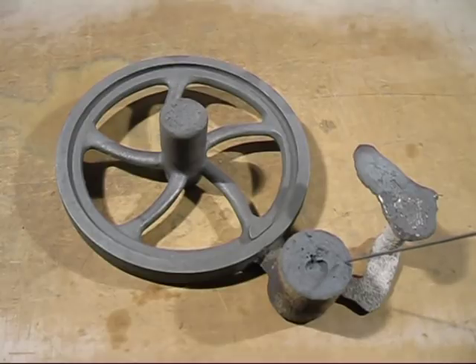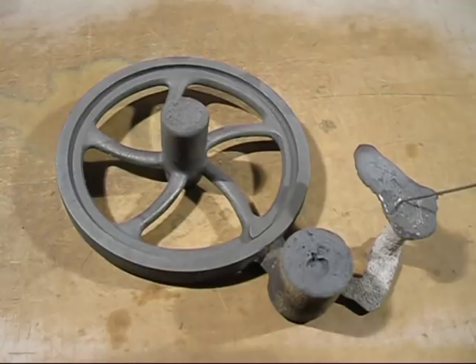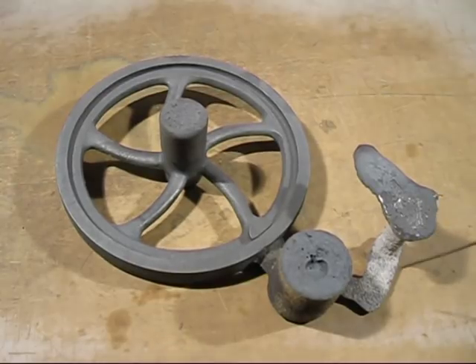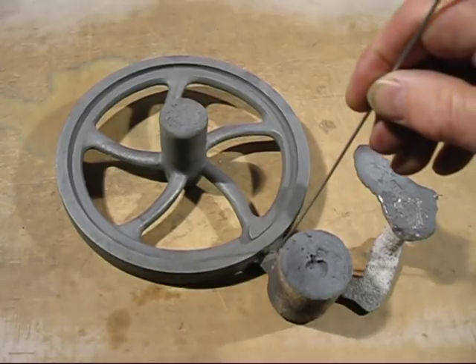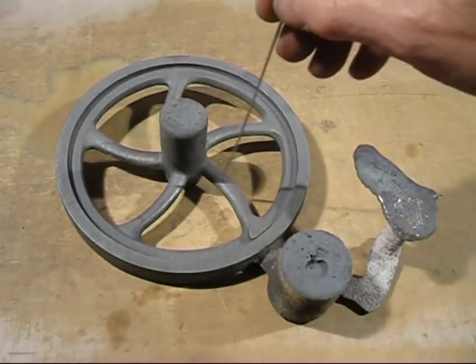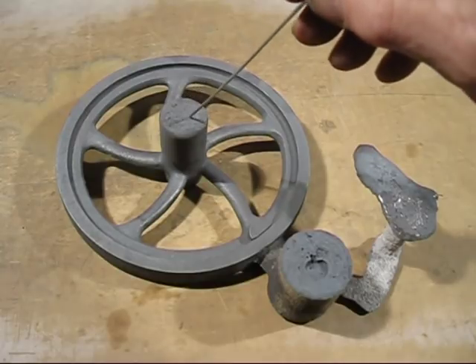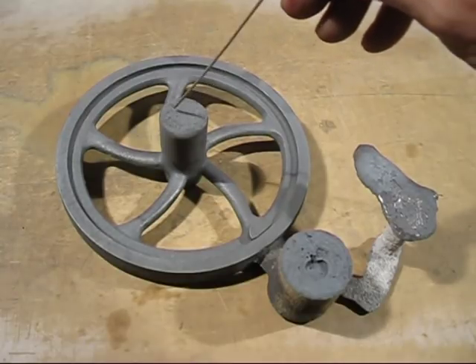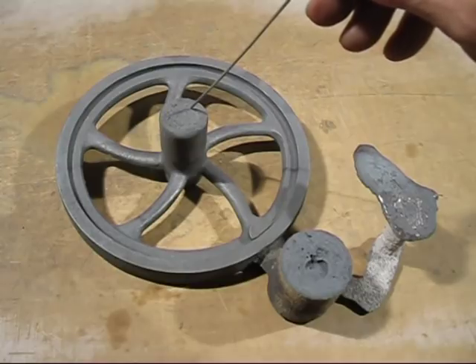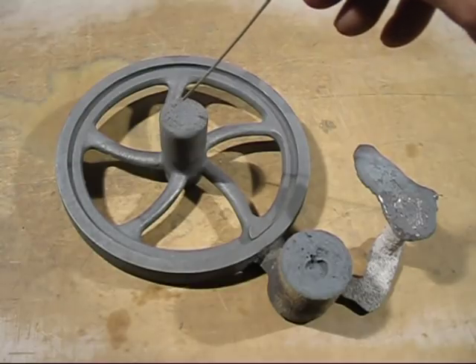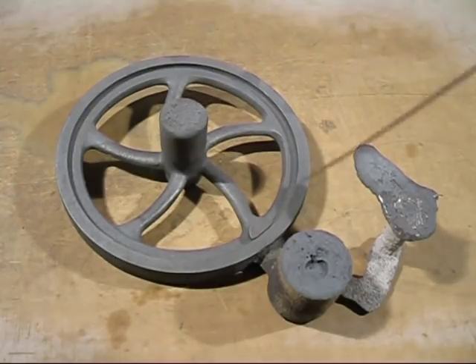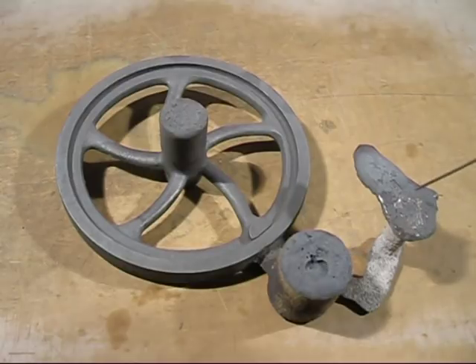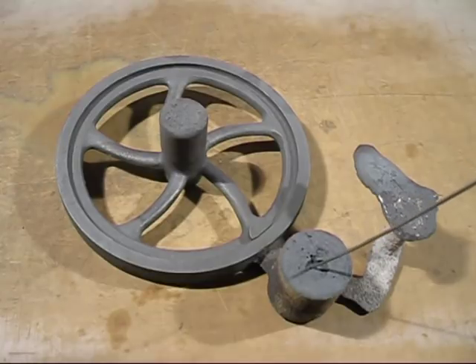Now the other thing you'll see in here, this is different from all the other moulds I've shown you. There is the sprue, and the metal comes in here, then it goes into the first riser, and then it goes through the gate and fills up the whole mould. And then the last part to fill up in the mould is this riser here. So what we've got here is a cold metal riser. This one doesn't shrink as much. But over here we've got the hot metal riser, because you're continually pouring in hot metal from the crucible. That shrinks a lot more.